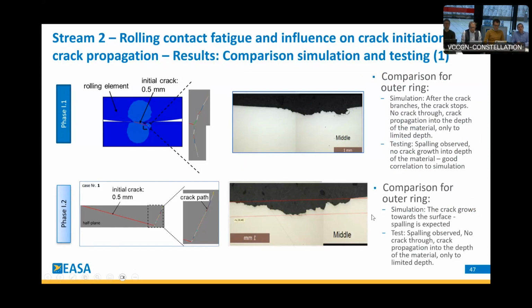Coming to the comparison between the results and the simulation. I start with phase 1. We have the rolling element, we have an initial crack of 0.5 millimeter, and you see the just mentioned increments, the calculation of the crack steps. And what we saw in the simulation is, after the crack branches, the crack stops. No crack through, the crack propagation in the depth of the material is limited, so it's a finite depth. And we would expect spalling, and at the end in the testing we observed spalling. No crack growth into the depth of the material, only, as I mentioned, if we cut it through, we have these finite depth, small cracks, but it's in general a good correlation to the simulation.